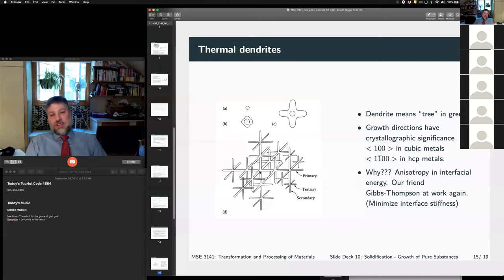Okay. So what happens is we get these thermal dendrites, right? So here's our nucleus. We get protrusions that form and they grow out. So these are the primary dendrite arms, right? Then we can get growth instabilities that happen along the primary dendrite arms growing into the supercooled region here. So the reading assignment is section 4.3. Right? So we get an instability that forms on these primary dendrite arms, and then we get secondary and then tertiary. So the dendritic structure forms, I think, one of the most beautiful shapes in nature.